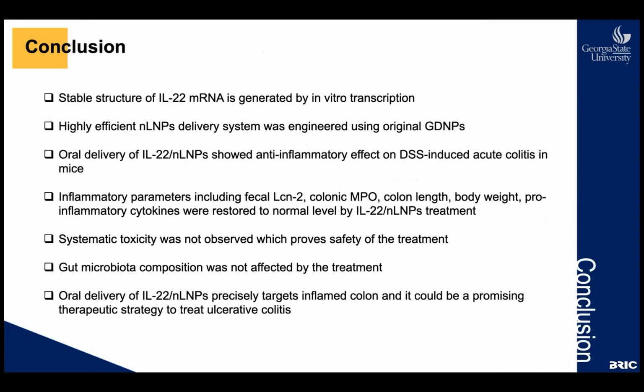To sum up, we have developed a stable synthetic IL-22 mRNA and encapsulated it within highly efficient lipid nanoparticles originated from the GDNPs. When we orally administered the IL-22 lipid nanoparticles to DSS-induced colitis mice, inflammatory parameters such as lipocalin-2, colonic MPO, and pro-inflammatory cytokine levels were reduced, and the body weight and the colon length were recovered to the level of healthy mice. We also tested the systemic toxicity of the IL-22 lipid nanoparticles, and biocompatibility and safety were proved for use as therapeutics. And overall, the oral delivery of IL-22 lipid nanoparticles precisely targets the inflamed colon and accelerates the healing phase without affecting gut microbial composition. And we assume that this novel delivery system could be a promising therapeutic strategy to treat ulcerative colitis. And that's it for my talk.